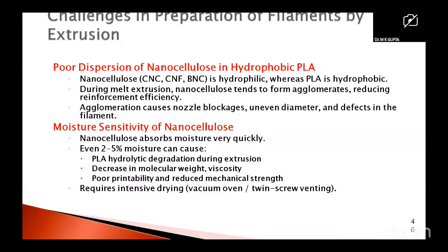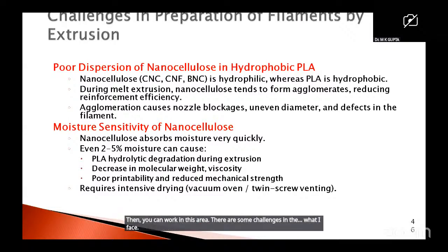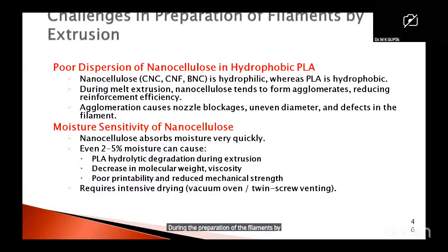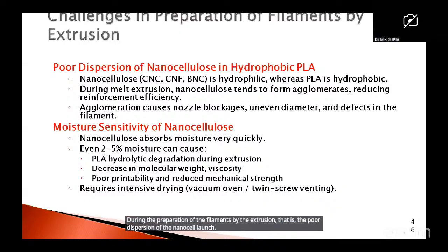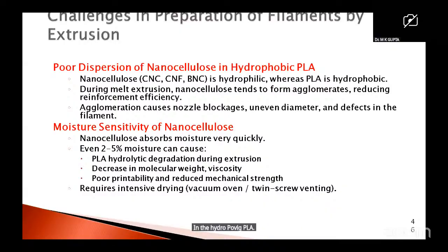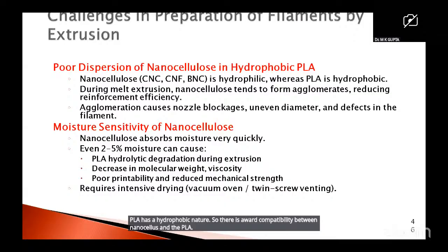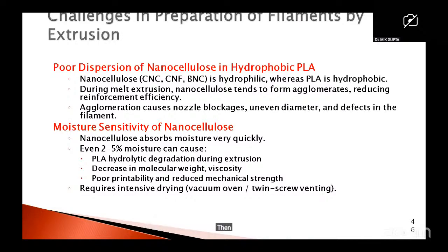There are some challenges I faced during the preparation of the filaments by extrusion, that is the poor dispersion of the nanocellulose in the hydrophobic PLA. The problem is the poor dispersion. The main reason for the poor dispersion of the nanocellulose is that nanocellulose has a hydrophilic nature, and on the other side, PLA has a hydrophobic nature. So there is a poor compatibility between nanocellulose and the PLA, resulting in poor dispersion of the nanocellulose. Moisture sensitivity of the nanocellulose: nanocellulose absorbs water or moisture very quickly.